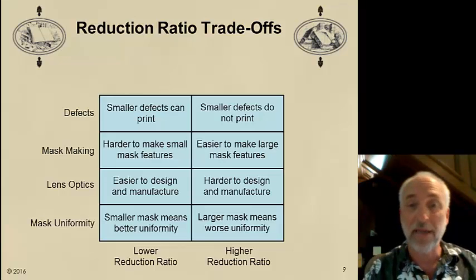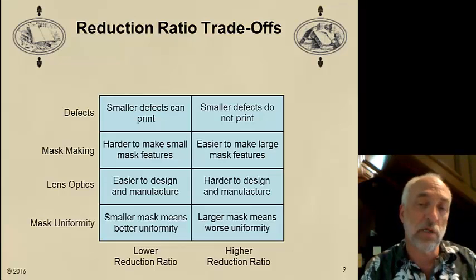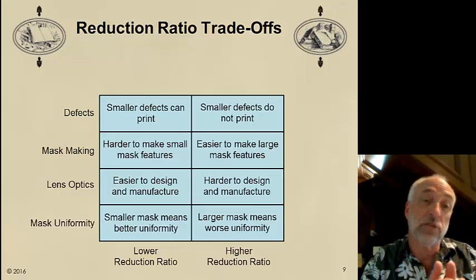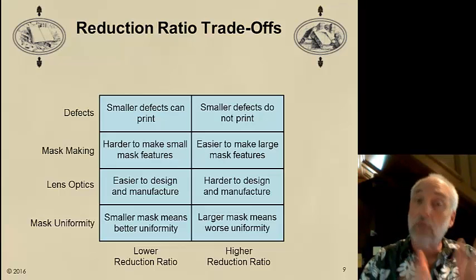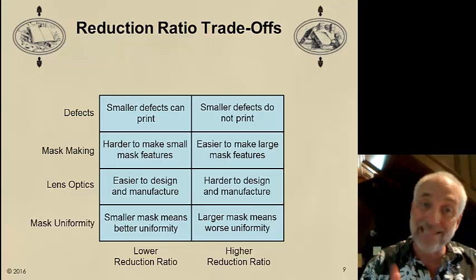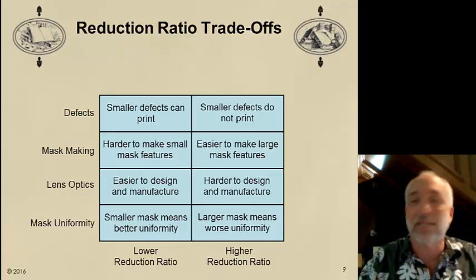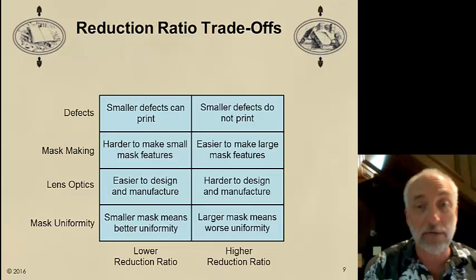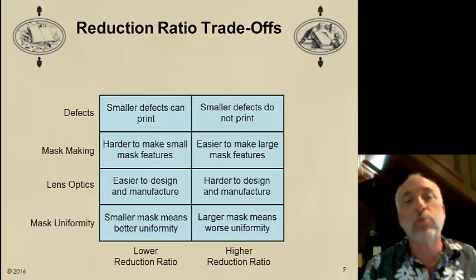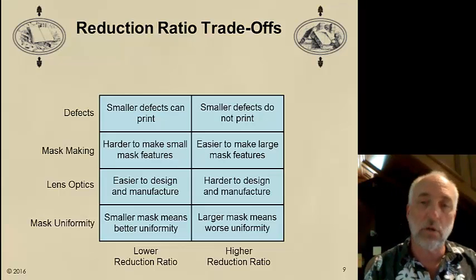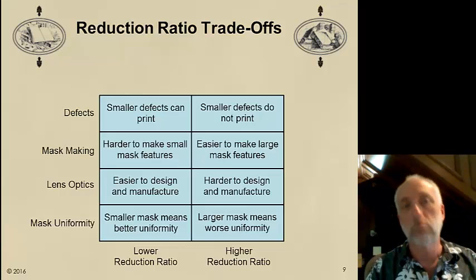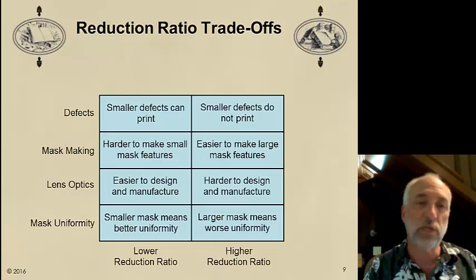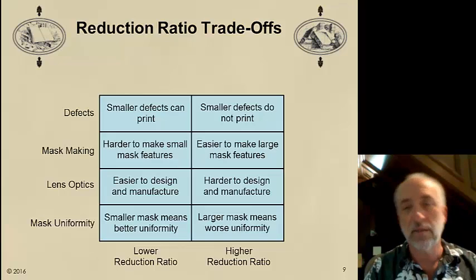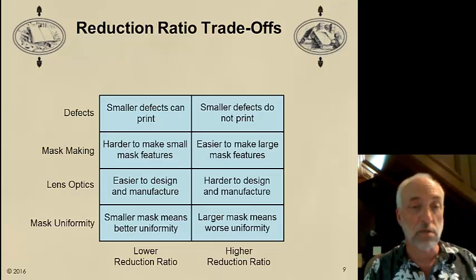For example, in mask making, if I have to print a feature, well, a higher reduction ratio means the features on the mask are larger. Larger features on the mask are easier to print. It makes the mask making easier if I use a higher reduction ratio. So again, that pushes us to want to make masks with a larger reduction ratio. Defects don't print as easily, and the mask making is easier.